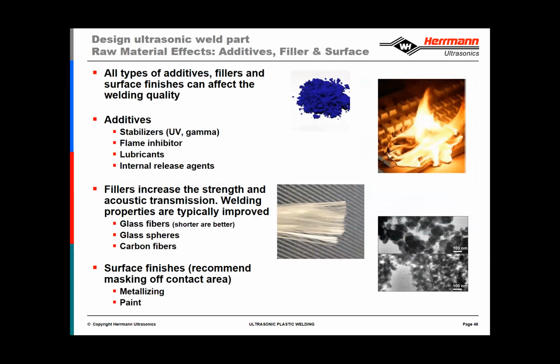So when the sonotrode is making contact with a glass-filled part, it will very often wear much quicker than contacting a non-filled part. The other downside is that the glass fibers, which are intended to strengthen the properties of the material, do not bridge across the weld area. They're usually very large, and they don't intermingle like they would in the molding process. So therefore, the joint or the weld area often does not have the same strength properties that you would see in the rest of the part. So in those instances, what we recommend is that the weld be up to or more than 1.5 times nominal wall thickness. So you make the joint larger in order to compensate for those strength deficiencies that you might see in the joint area.